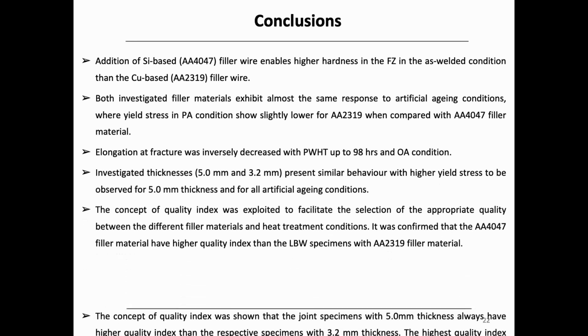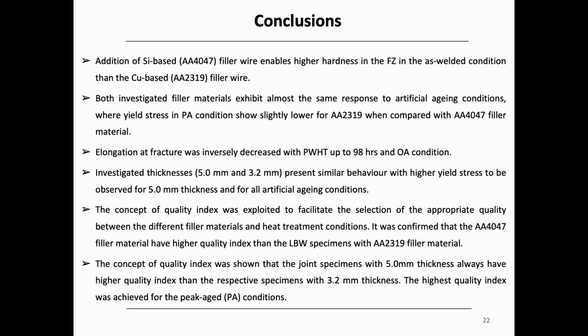Addition of silicon, if we use the 4047 filler wire, enables higher hardness in the fusion zone in the as-welded condition than the copper-based wire, for example 2319. Both investigated filler materials exhibit almost the same response to artificial aging condition, where yield stress in peak aging condition is slightly lower for the wire 2319 when compared with wire 4047. Elongation at fracture decreased with post-weld heat treatment up to 98 hours, in the overaging condition. Both investigated thicknesses present similar behavior, with higher yield stress observed for 5.0 millimeter thickness, for all artificial aging conditions.